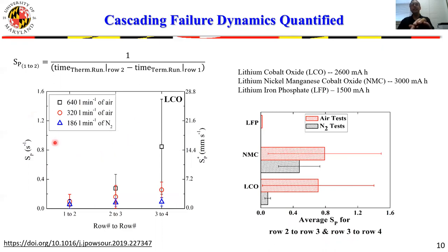We found that in the test that did not involve flaming combustion in nitrogen, the propagation from row to row was very steady. It went through the array at a very steady rate. When we added air, especially air that was added at a high rate, we found that this propagation accelerated very quickly in time. And actually at the end, we observed propagation rates that were an order of magnitude larger than those observed in nitrogen. The reason for this is, of course, that in this case the flaming combustion was actually present in the tunnel. It contributed to the heating of the cell adjacent to the cell that underwent thermal runaway and basically accelerated their failure this way. So you have a considerable effect of this flaming combustion, provided that the oxygen is available.